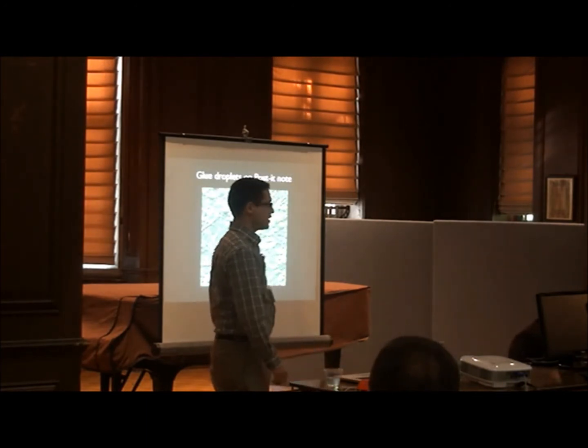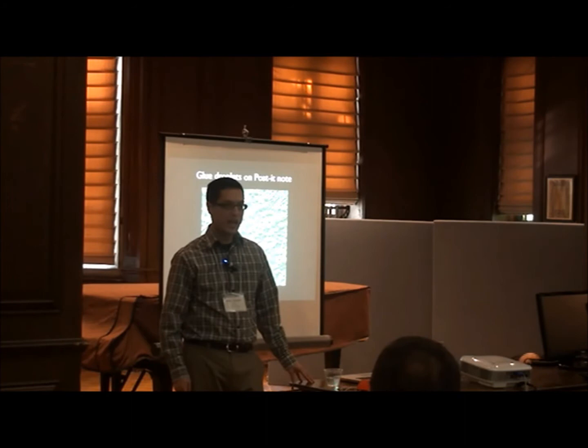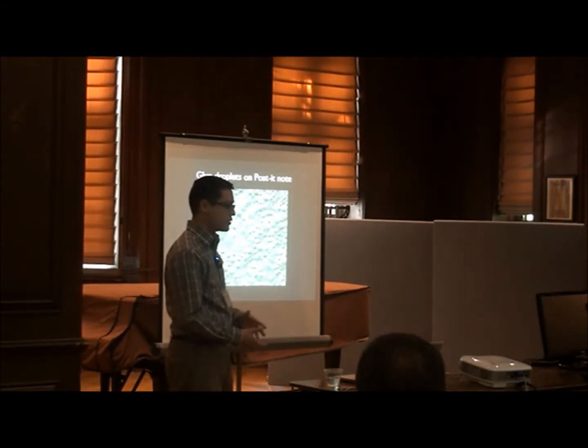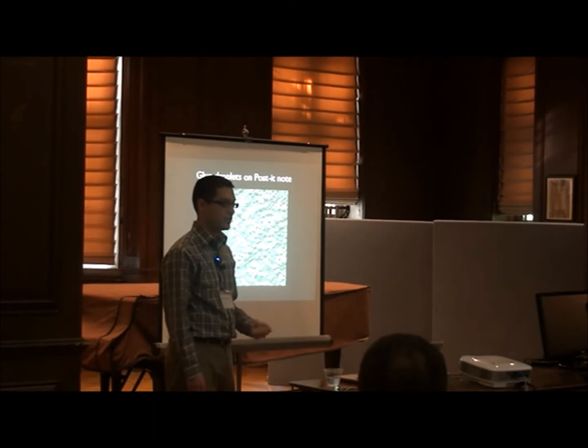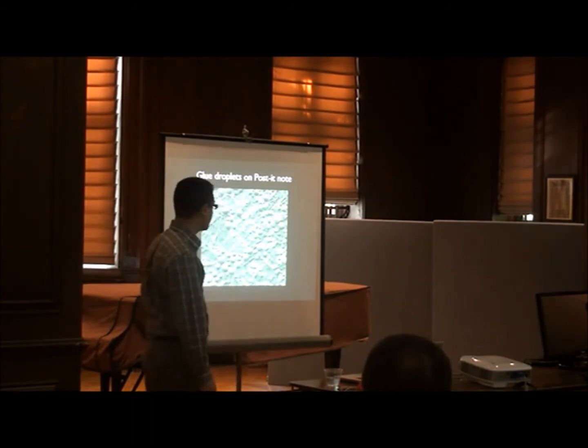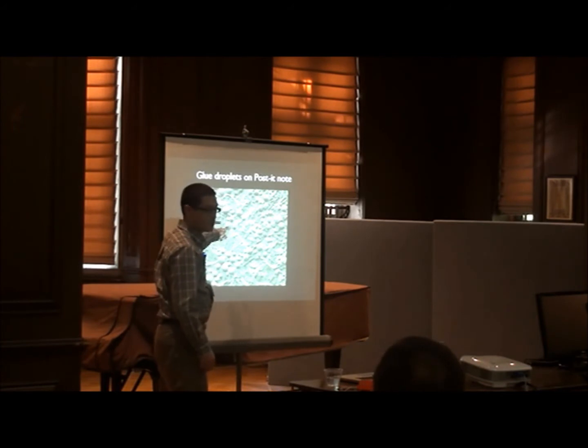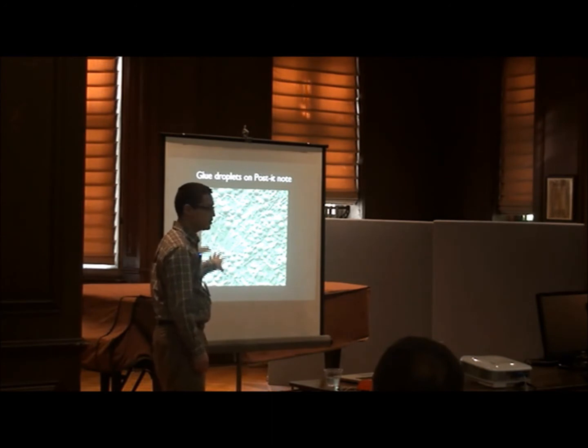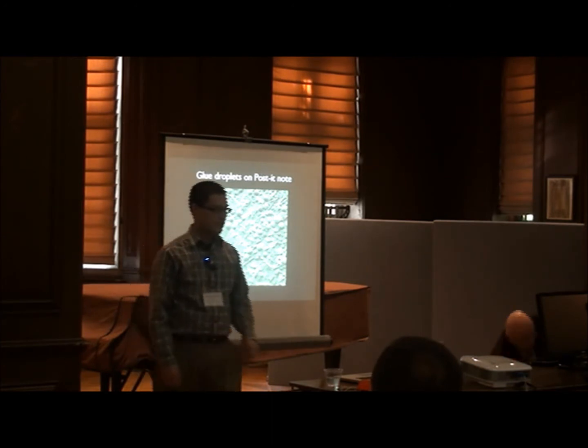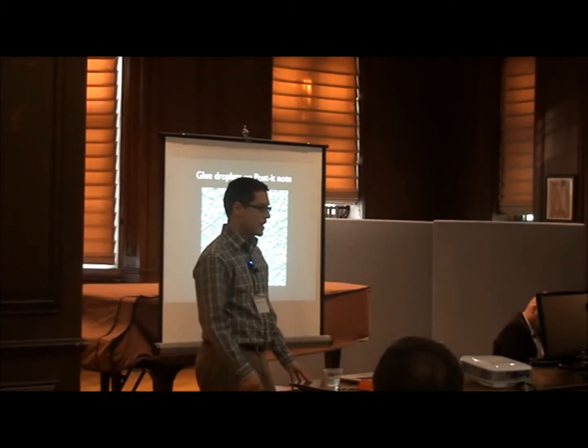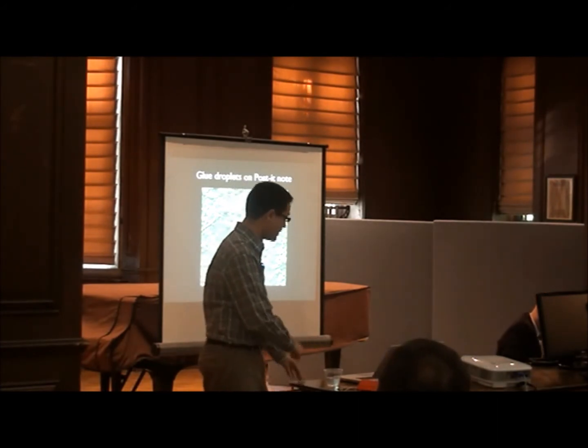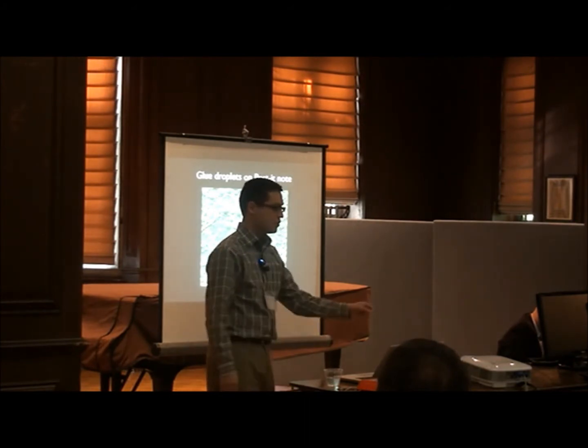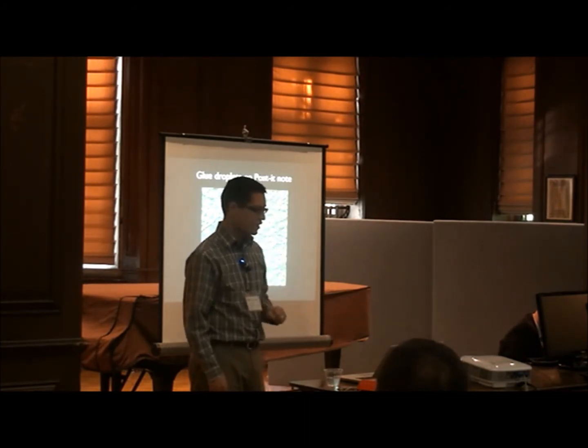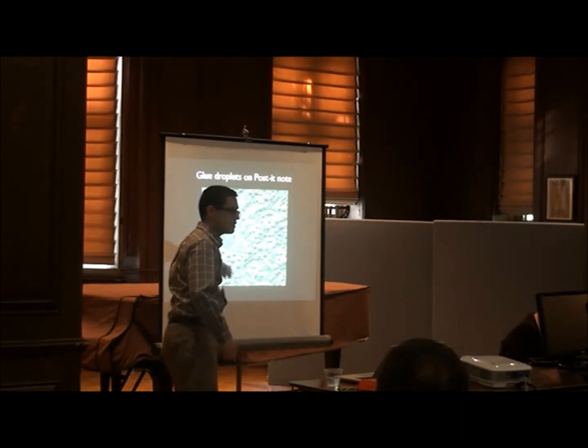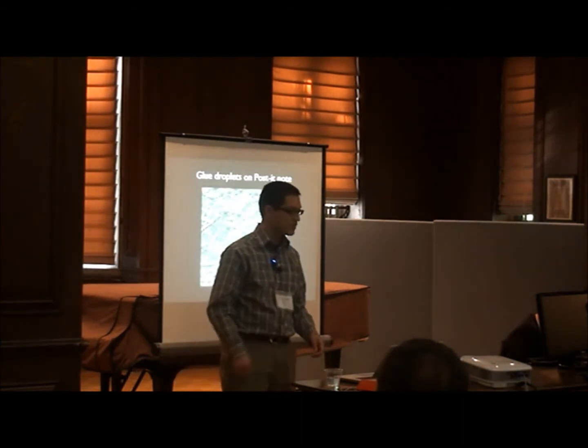And finally, a lot of engineered materials have surface topography or surface structures that are very directly related to their function. And this example shows a Post-it note. And you can see the paper fibers of the Post-it note. You can also see discrete glue droplets. And the distribution of glue droplets and the fact that they have different sizes tells you a lot about how a Post-it note works. The fact that it only adheres weakly to a surface, because as you press it down, perhaps some of the bigger drops burst first, and then there's still some remaining smaller ones for the next time you pick it up and put it down.